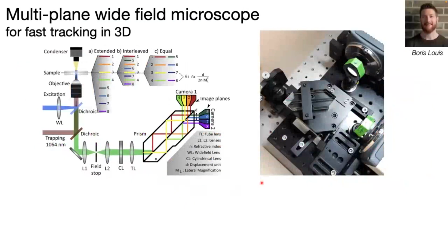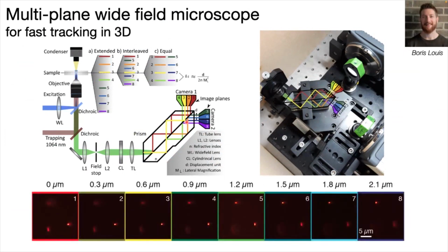And to do that, we use a multiplane wide field setup. And the special thing about this multiplane setup is on the detection path. So we have this prism, and what the prism does is that it separates the emission that comes from the objective into 8 different paths that have a different length, which means that in practice you are imaging 8 different planes at the same time, okay? And this is what you get. So some molecules will be in focus on the first planes, and then you see that on the last planes they are out of focus, and the other way around with some molecules.